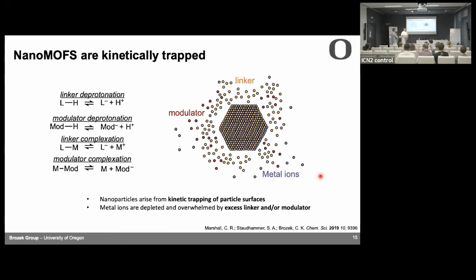Yeah, so that's our hypothesis. You don't have a good technique for seeing that. We think the reason the smaller particles undergo spin crossover at a lower temperature is that you have more of the surface, and the surface metal ligand bonds are more flexible, and so it can happen. So we have a lot of indirect evidence. For example, the fact that the Wang-Rees parameter is smaller in the smaller nanocrystals is another example of maybe you have more surface. I also think the size-dependent band gap reflects a more flexible surface, but we don't have direct evidence of that yet. We're working on it though. Really nice, thank you.